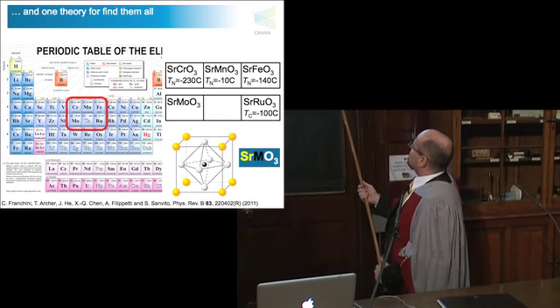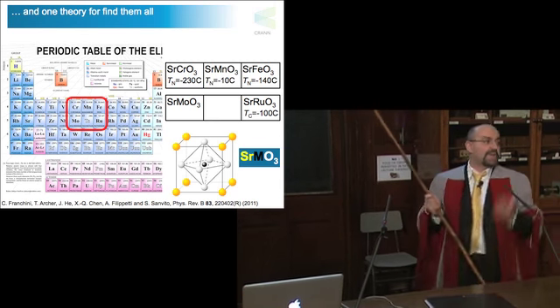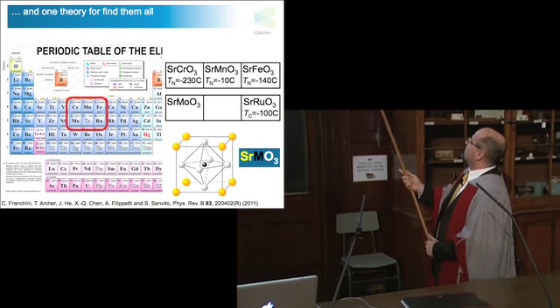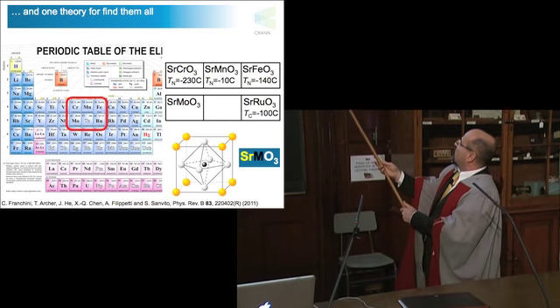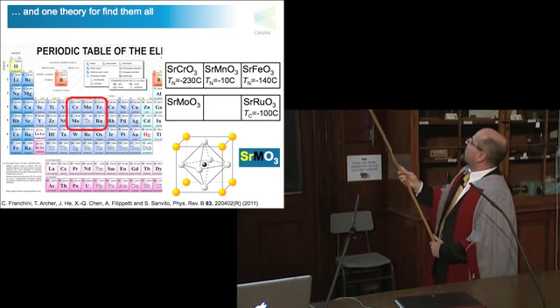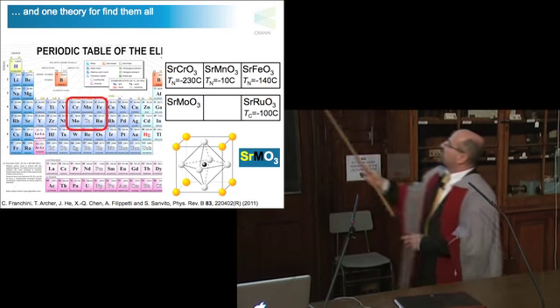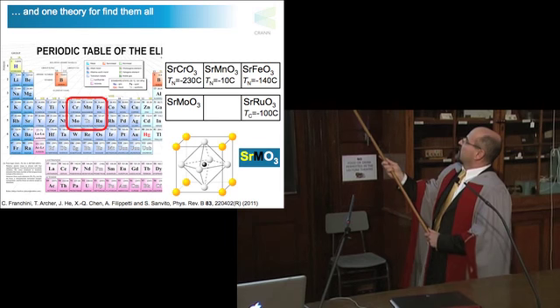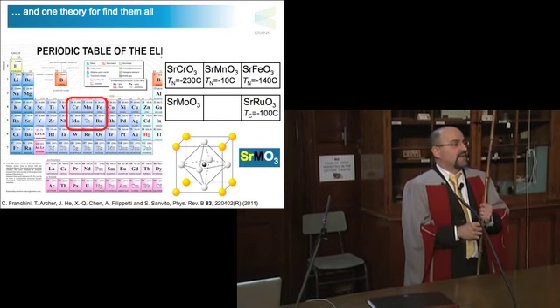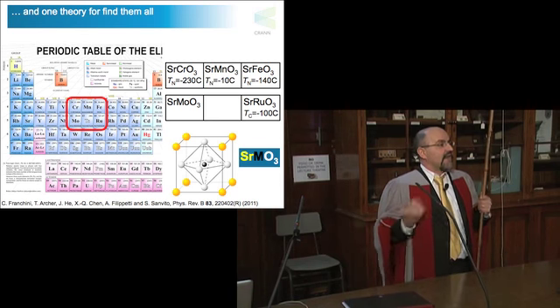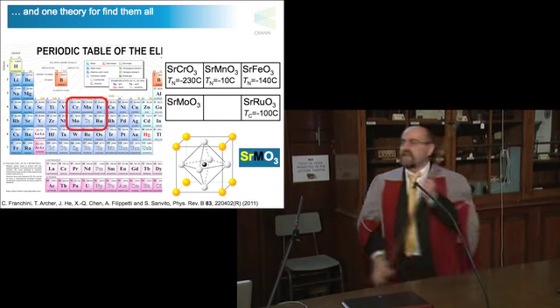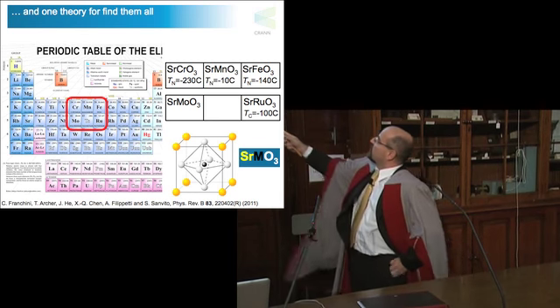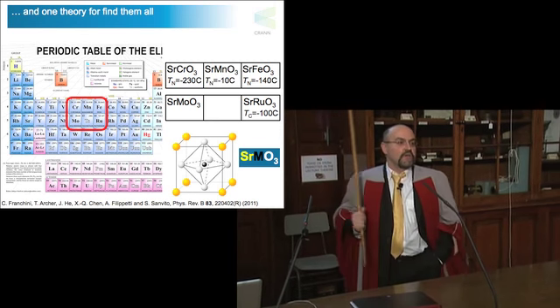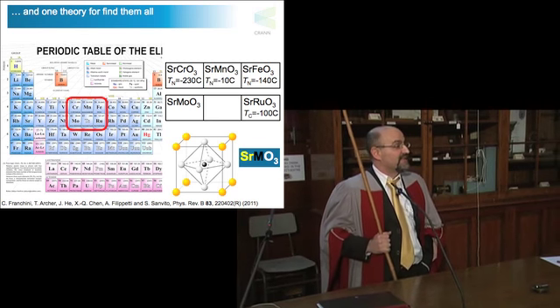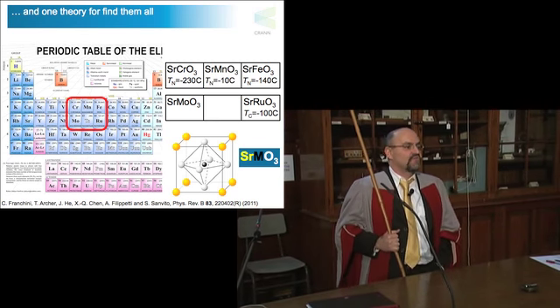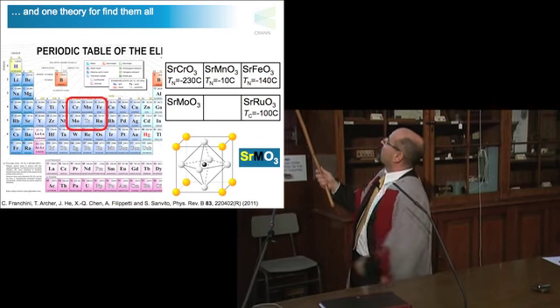So if you take this crystal, which is the perovskite, and you take one particular way you can form this crystal, where strontium fills the yellow balls, oxygen the white ones, and another material that you pick in this region of the periodic table fills the black one, then you have a transition metal perovskite, and you have magnetism. And look what happened. If the black atom is chromium, you get a magnet, which is magnetic at minus 230 degrees. So it's probably magnetic only on Jupiter or, I don't know, Pluto, one of the cold planets.